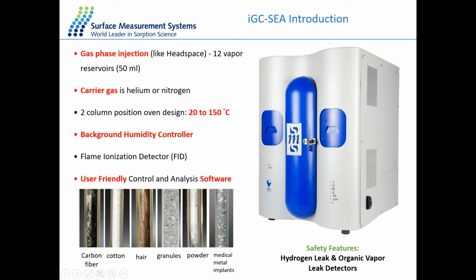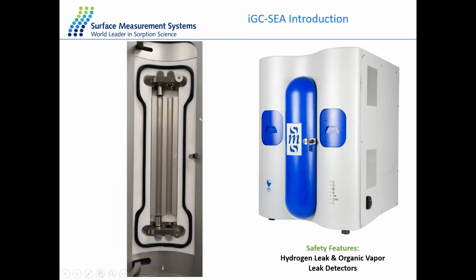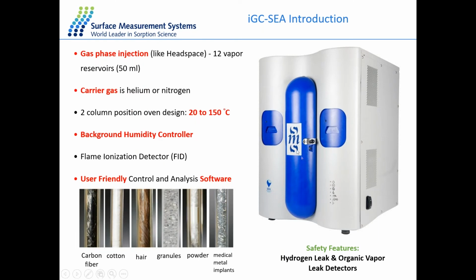The system comes with either a helium or nitrogen carrier gas. When you open the door in the middle, what you'll find is where you put your columns. We have a 2-position column, 1 and 2, and this is surrounded by a column oven. The column oven goes from 20 degrees to 150 degrees.